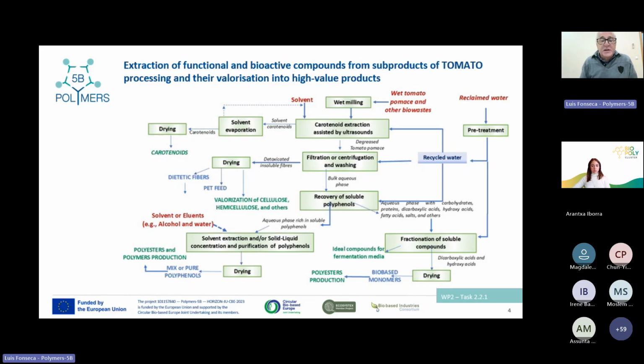This direct strategy showed that it was impossible, because when we dry the bio-based monomer, you obtain a thermoset plastic that is difficult or impossible to work with easily, at least at low temperatures, and we dried this at 65 degrees. So we had to start again, and then move to a cascade integrated process in which we separate several compounds, as you can see in the diagram.